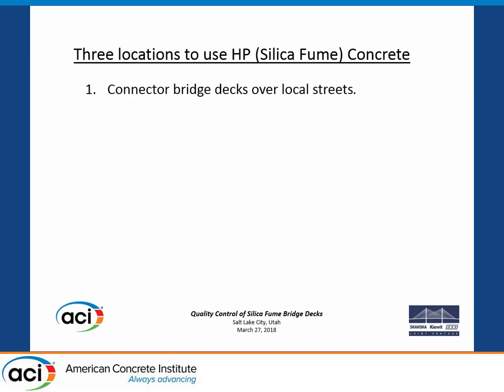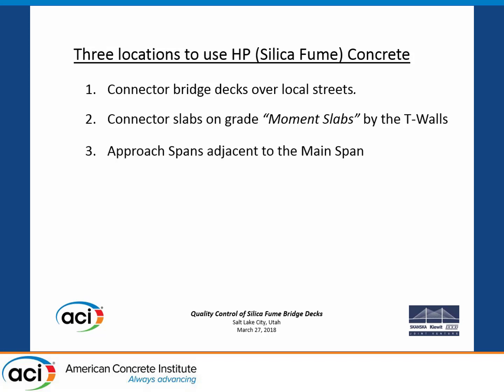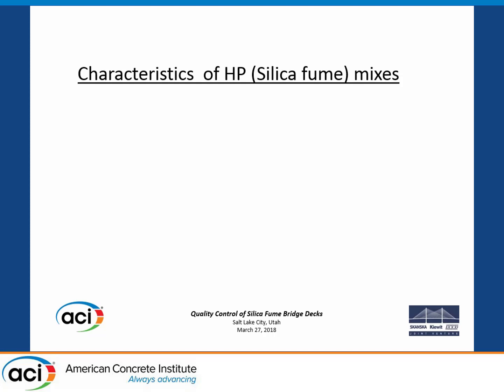3 locations we used the HP. We used it on the connector decks over local streets. All those T-wall structures that connected us to the existing Brooklyn Queens Expressway, they had local streets that they had to span over. They used the HP on those. Connector slabs on grade, moment slabs, are something I'll show you. They're the slabs adjacent to the T-walls that have to be structural members. And then the approach slabs. These are 1,000 foot long. They're decks on top of precast vault tees. And the total yardage is 14,000, and we had 97 placements.